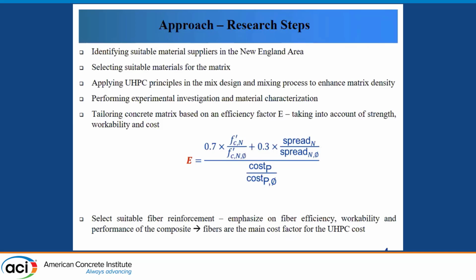Then tailoring the concrete matrix based on the efficiency factor. It takes account of compressive strength, workability, and cost. It gives more weight to the compressive strength and less weight to the spread. After selecting the suitable matrix, we select the suitable fibers, with emphasis being placed on the fiber efficiency, workability, and performance of the composite, as fibers are the most expensive ingredients in the UHPC.